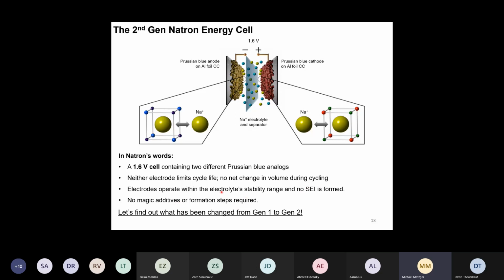And the other really cool thing is you also don't need a formation step in their technology. So, we learned in the other classes that people typically do a very slow cycle after assembly of the battery cell, where a lot of gases are generated, and you form this passivating layer on the electrode, which is, of course, time consuming, and time is money. So it's really a nice fact that in their battery technology, you don't need a formation step.